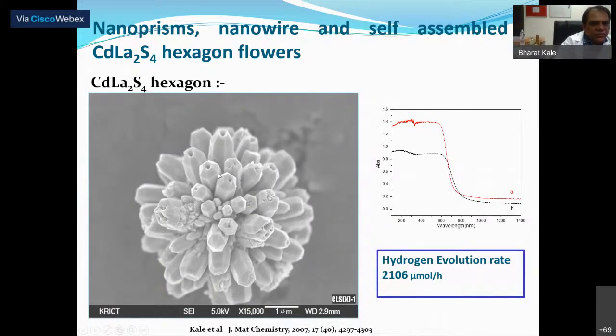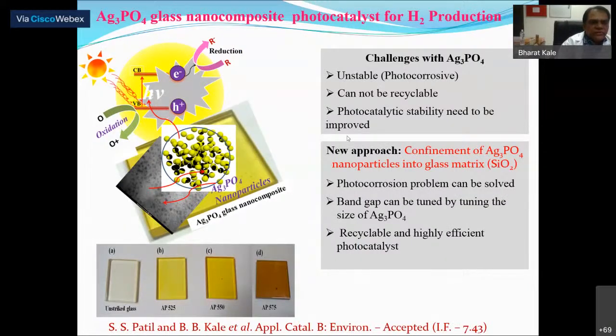Then this is a very phase pure compound, a new compound we have developed. We have determined the crystal structure and all these things. We found this structure is very stable and gives very stable photocatalytic activity. Then, for the first time, we have embedded Ag3PO4 nanoparticles in glass. This is the first report we can find in the literature that Ag3PO4 nanoparticles can be embedded in glass, which gave good photocatalytic activity.